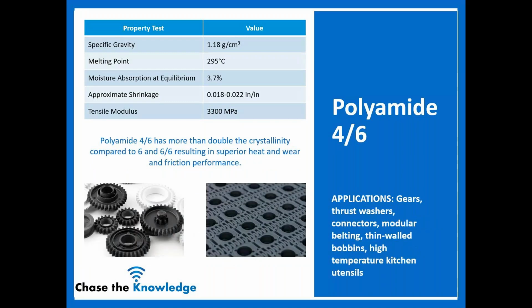Okay, and then the last one we're going to talk about briefly, maybe a little lesser known, people aren't as familiar, is polyamide 4.6. This is going to be the shortest chain of the ones that we talk about, so it's going to be the highest temperature. It also has about double the crystallinity. So the overall amount of crystal structures within a 4.6 is double that of a 6 and a 6.6. This results in superior heat. If we look at the melt point, 295.